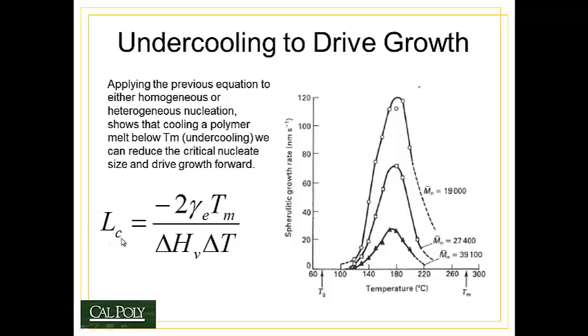The critical parameter for forming a stable nucleate in heterogeneous nucleation of a polymer melt is equal to -2 times the edge surface energy of that lamellae in the growth direction times the melting point of the polymer divided by the enthalpy change of the system divided by the change in temperature. In other words, if I can cool the polymer melt below the melting point, I lower the size of the critical nucleate to form and make nucleation more likely.